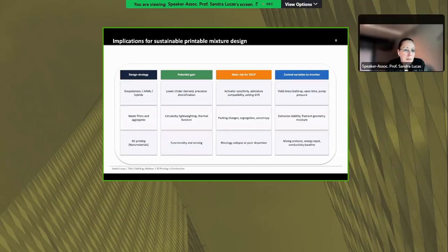For example, when you go for alkali activated materials, there's still the open time that needs to be controlled, the pump pressure. There are some aspects with the activator sensitivity, for example, which is still a main risk. For the fillers and aggregates, you still have the segregation aspects to control, the anisotropy, the packing changes, because you have a material that doesn't always pack in the same way. So you have changes in porosity and the extrusion stability, for example. And with the multifunctional materials or the functional materials, which we call the 4D printing, you still have a lot of problems with the mixing control. So also the pore dispersion of these materials and the cost.